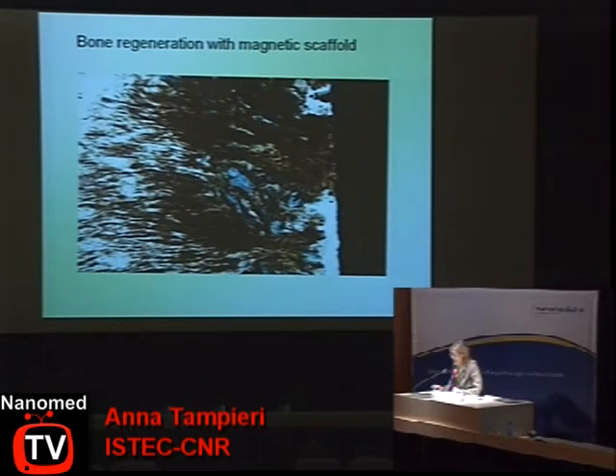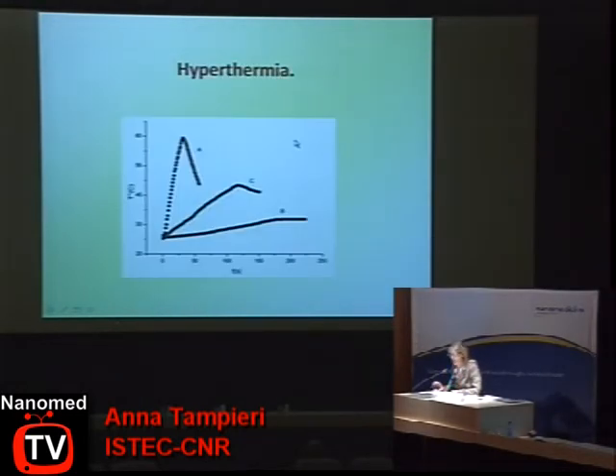This is an image of the bone regeneration in a big defect in the rabbit with a magnet, that is this black line. And as you can see, the bone forms with a highly oriented lamellar structure. This powder is also characterized by incredibly high hyperthermia, so we can develop this phase also for therapeutical intent.